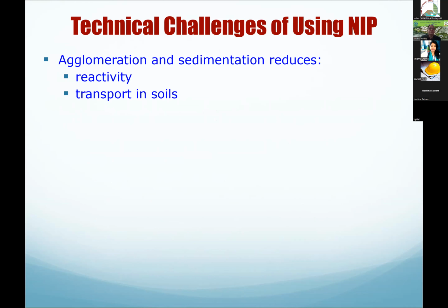But we have problems with using nanoiron particles. What are the biggest problems? These nanoiron particles don't want to exist as nanoparticles. They try to attract each other. They agglomerate. Agglomerate means they come together and become aggregates. And as you saw, the density is higher than 1, and they settle down, sedimentation. Even in the container, they come together, form these lumps, and then settle down. If you have that kind of problem, you cannot introduce it, right? So you cannot transport it in the soil, and the reactivity is based on the nano size; when it agglomerates, it won't be a nanoparticle. So that's the problem.